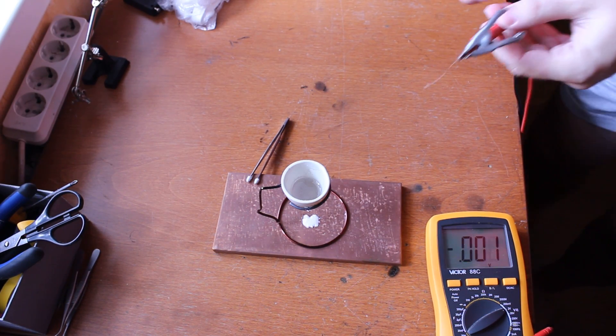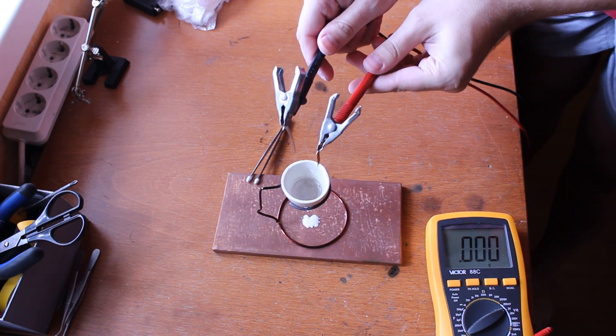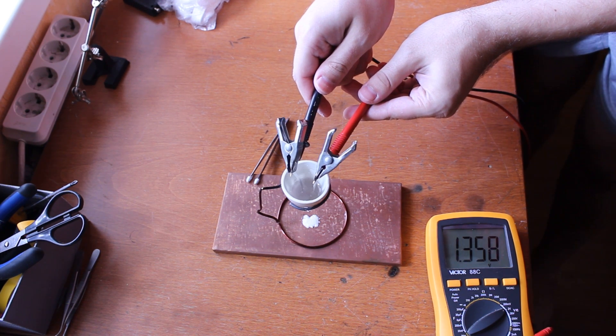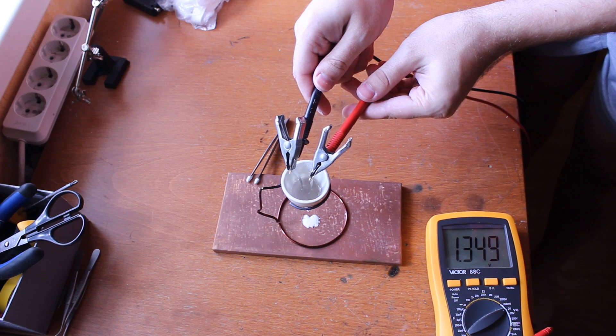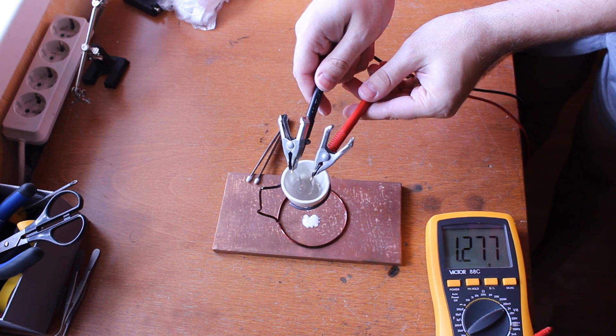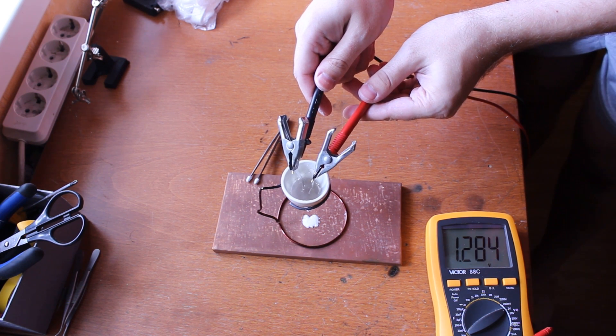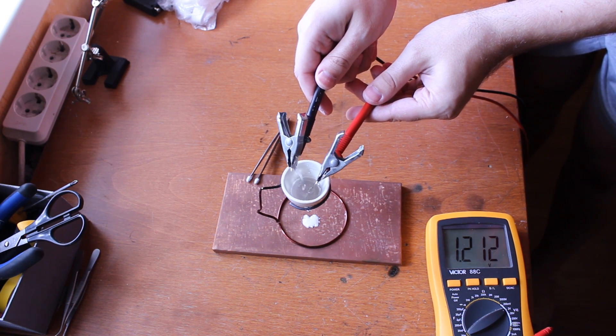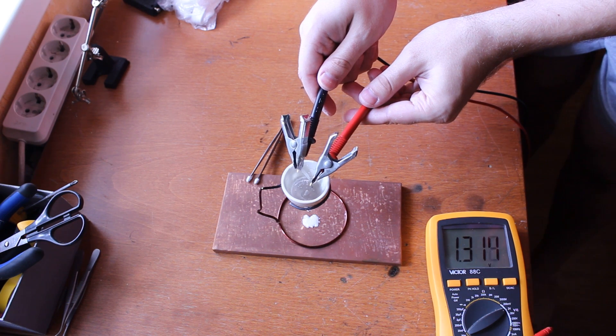Time for a proof of concept. Take magnesium into the negative hand and nickel into the positive hand and we get a voltage. Now a fresh and hot electrolyte should give you about 1.6 volts, but since it's already cooled down a little, there's a crust of salt forming on the electrodes and the voltage is a little bit lower.